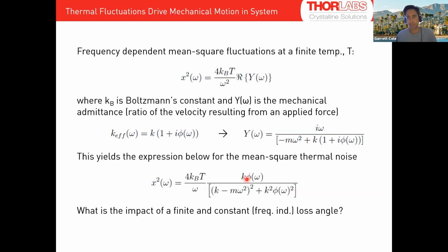So we all know Young's modulus is the stiffness of a body, but what we don't typically think about is there's a phase lag. If you take a rubber or viscoelastic solid and you push on it, of course, it takes some time for it to respond, but everything does that. Diamond does it, right? I mean, the hardest materials you can think of, you push on it, there's a slight phase lag, but it's so small, we typically totally ignore it. But in this application, it's really going to be important. So that's something new that you can learn today. Everything's soft, everything's viscoelastic at some level, right?